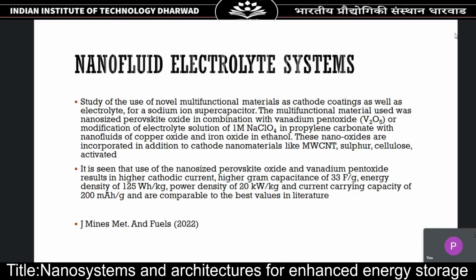So we got an energy density of 125 watt hour per kg, power density of 20 kilowatt per kg, and a current carrying capacity of 200 milliampere hours per gram. So these are comparable to some of the best values in literature.